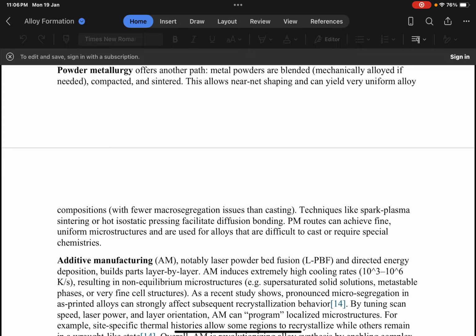Techniques like spark plasma sintering or hot isostatic pressing facilitate diffusion bonding. PM routes can achieve fine uniform microstructure and are used for alloys that are difficult to cast or require special chemistries.